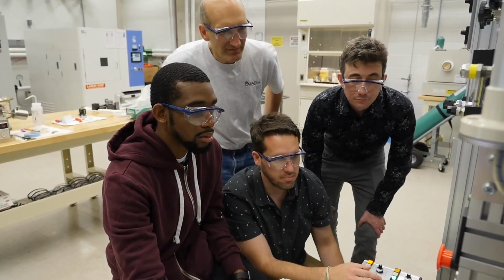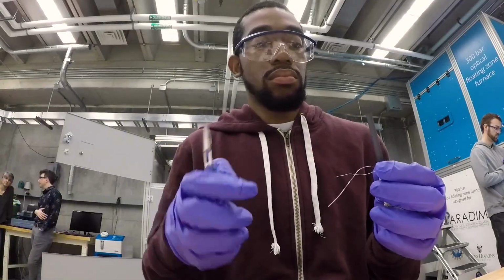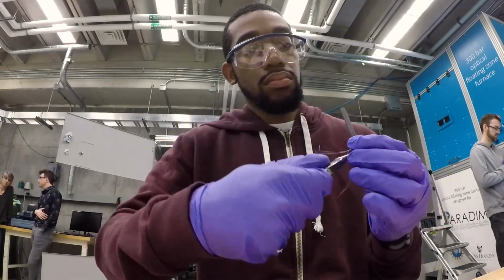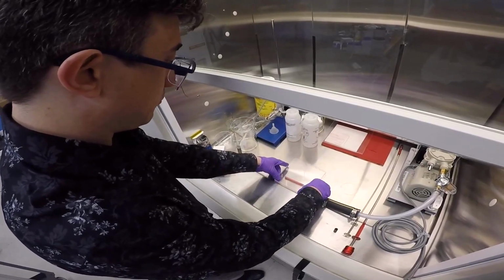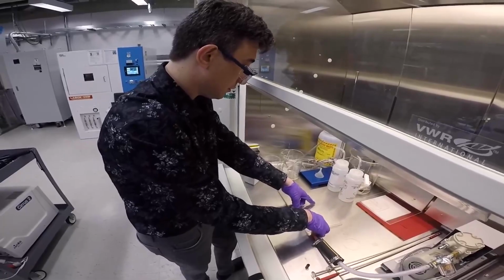A lot of these crystals, they're not necessarily like we learned to do in science class, where we grow rock candy or we evaporate water to grow salt single crystals. A lot of these materials have very high melting points or very high vapor pressures. Rhenium silicide has an incredibly high melting point. In order to grow a crystal of it, we need to get to 3,600 degrees Fahrenheit. That's hot enough to melt bricks.